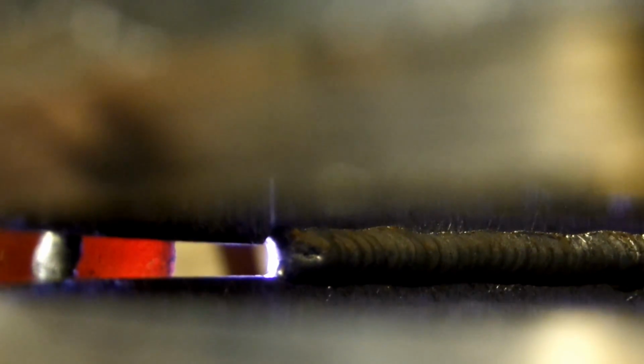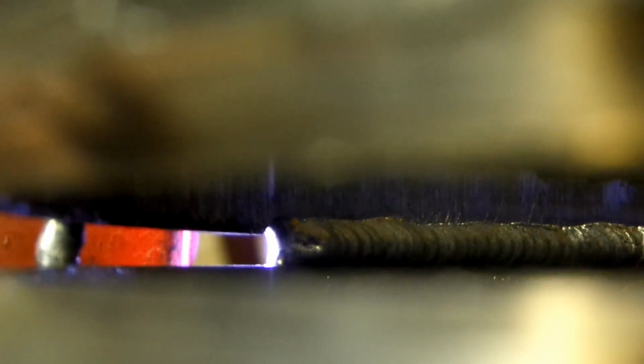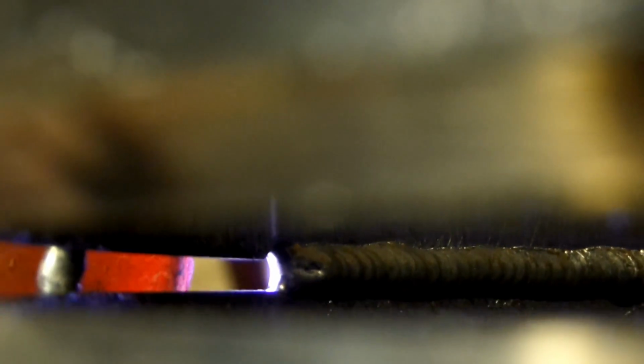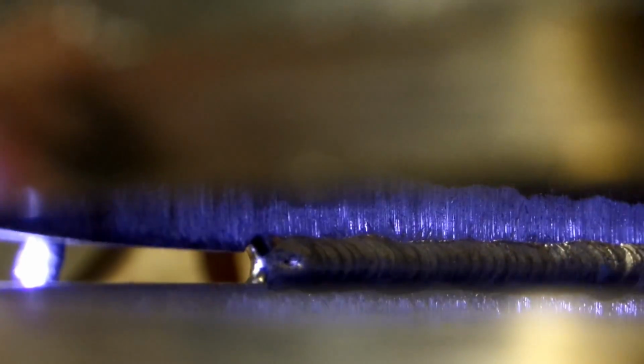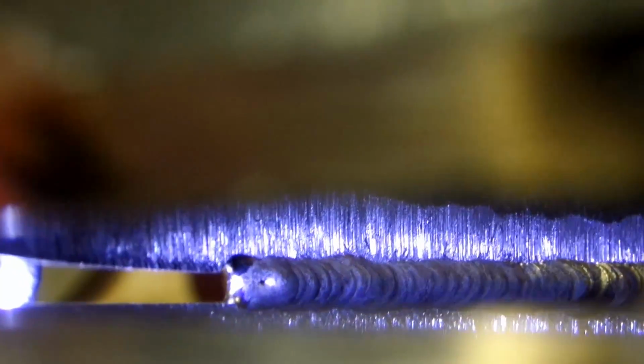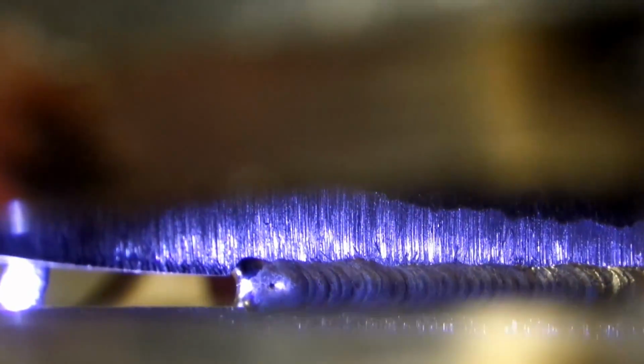You have to feather your starts and stops with this Inconel, Hastelloy, these nickel alloys. You're going to have a lot of difficulty trying to burn out that pinhole. It's also a fair amount of metal to burn out. It's an easy way to get discoloration, with a lot of heat trying to melt that pinhole out. So you feather your starts and stops.